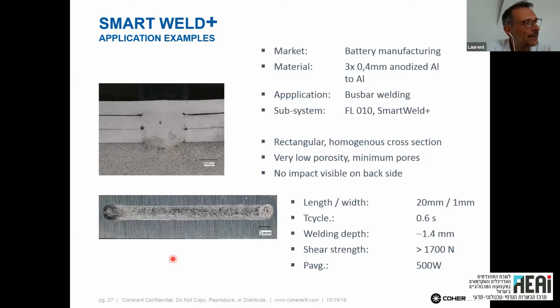There is a little bit of gap, as you can see, and this is also the reason why if you look at the cross section, you will find some porosities, but it's quite low. We minimize the number of pores. The cosmetic aspect of the weld is also not so bad. Aluminum is always difficult to weld, but because we manage the melting pool, we have something quite stable. And at the end, from a cosmetic aspect, it's quite nice.